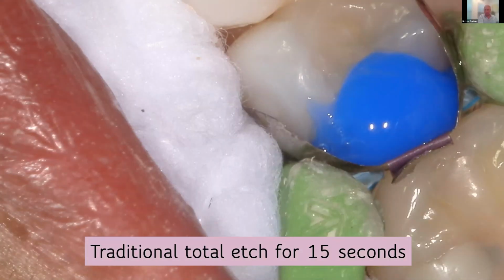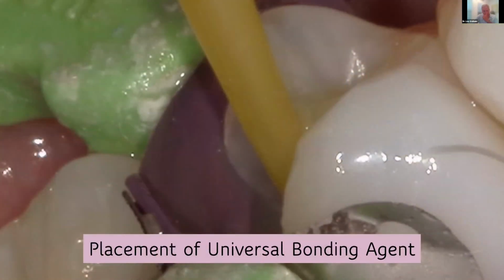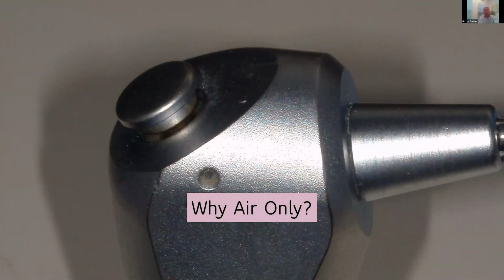After I've cleansed it, now I'm going to total etch for 15 seconds. After I rinse that area, surgical suction and blot dry, I then place my universal bonding agent. Yes, I'm a universal bonding agent user, and I will scrub the area for a full 20 seconds and time it. I'm scrubbing the entire area and the margins for 20 seconds. And now I'm going to air dry routinely for 10 seconds my bonding agent, not 2 seconds, but 10 seconds.